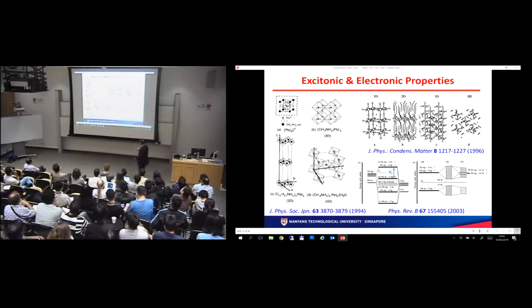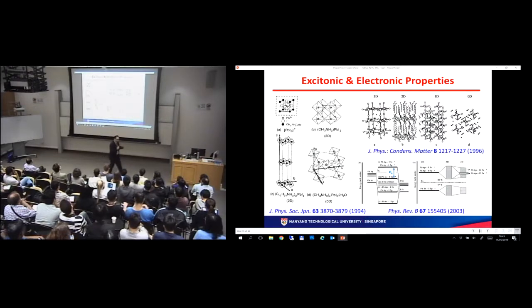And the band structure was also calculated. Now, the interesting thing is that the band gap comes about because of the anti-bonding states arising from the mixing of the lead and the iodide systems. And this is a consequence of the strong spin-orbit coupling, and it gives you very interesting properties, which I will talk more about in terms of the defect tolerance of this particular system.